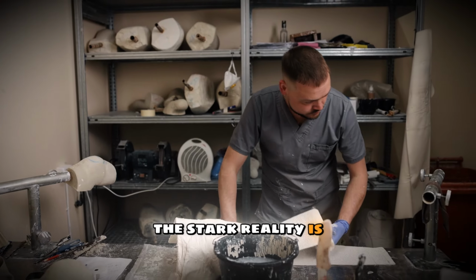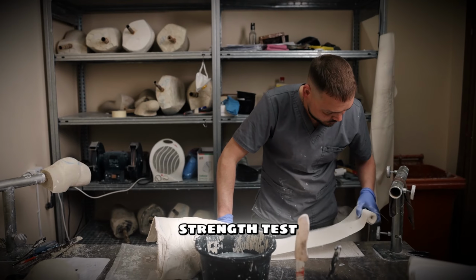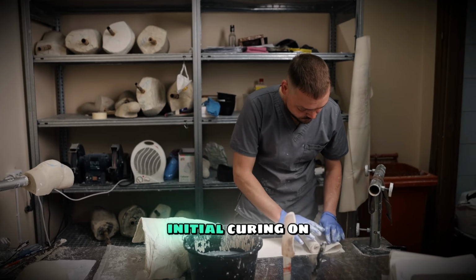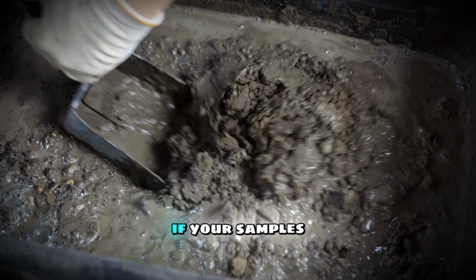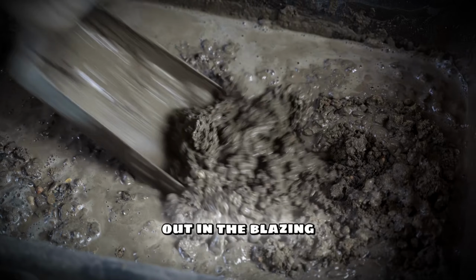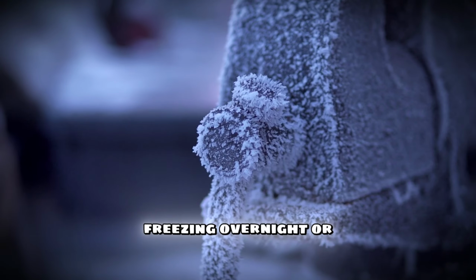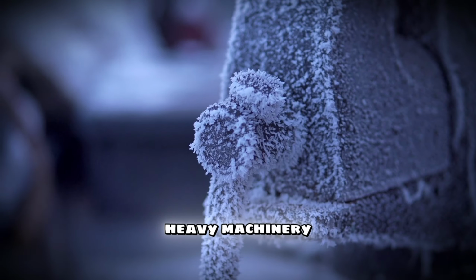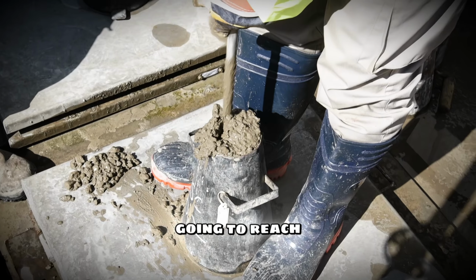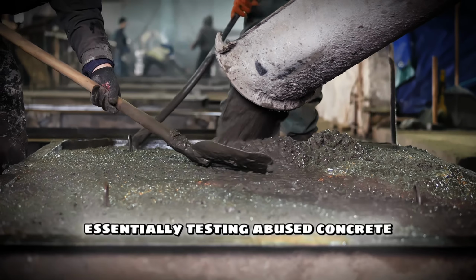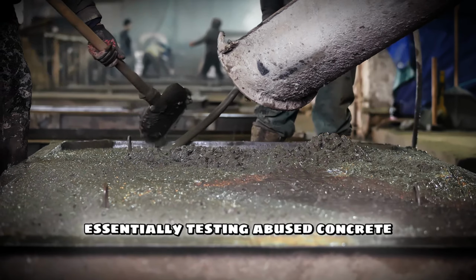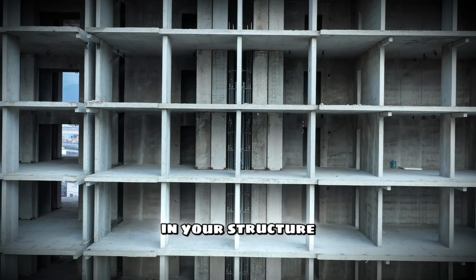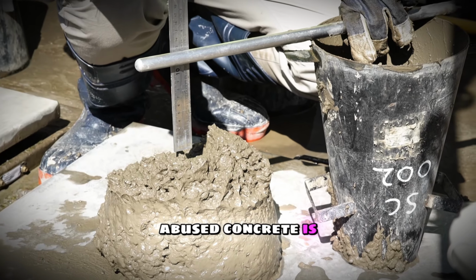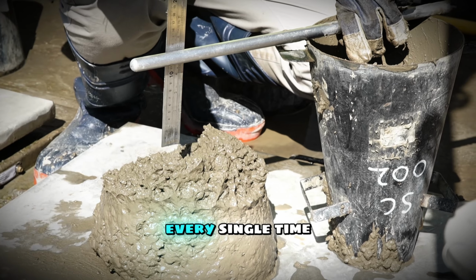The stark reality is that the vast majority of low-strength test results are caused by improper initial curing on the job site. If your samples are left sitting out in the blazing summer heat, freezing overnight, or vibrating next to heavy machinery, they are never going to reach their true strength potential. You are essentially testing abused concrete, not the concrete that is actually in your structure. And that abused concrete is going to give you a failing grade every single time.